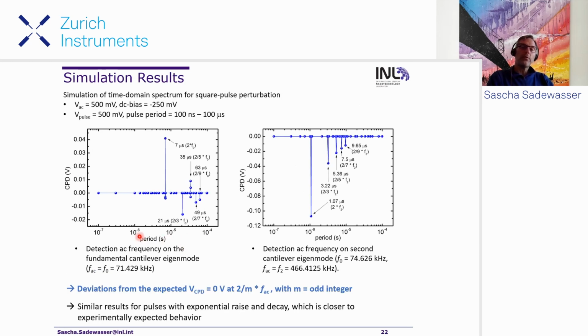So when we then vary the period of our pulses, we get these spikes that I just explained. This one here, but actually we get them at higher frequencies as well. And this goes in a systematic way. So this is 2 times the AC frequency, and then we see it at 2/3, 2/5, and 2/7 of the AC frequency.